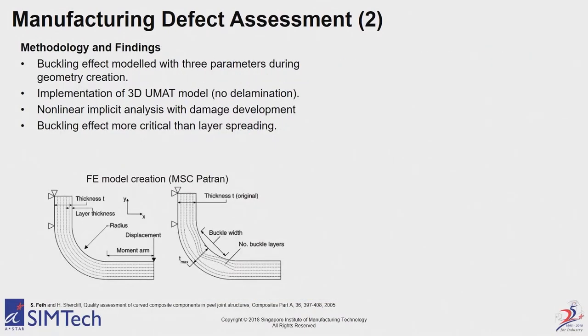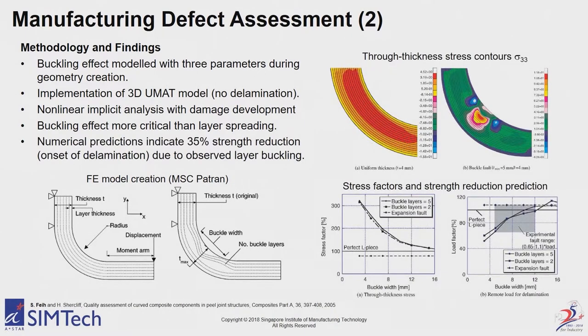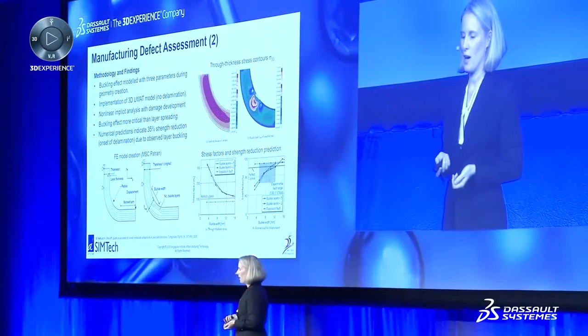So we actually generated some models, and you will see this was, again, early 2000s. We generated them with Patran. And we looked at wrinkles, and we looked at layer spreading, and we did fairly simple stress analysis at that point with in-plane composite damage. And the one thing is, if you have a nicely aligned layer, no wrinkles, nice spreading, you get a very nice stress profile. If you have wrinkles present, the stress concentration factor increases significantly. So here in the picture, if you can see the number, by about a factor of 2.5.